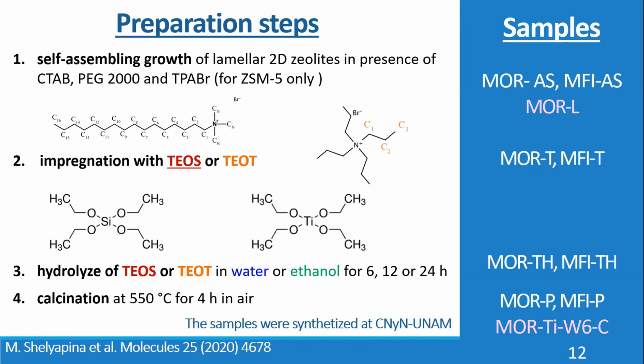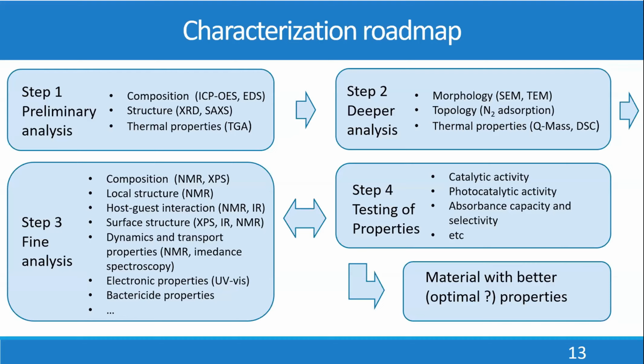Then hydrolysis occurs to form either SiO2 or TiO2 oxides between these layers, and calcination to evacuate the organics. All the samples were synthesized by our colleagues in the Center for Nanoscience and Nanotechnology at UNAM in Mexico, but all the studies were carried out at our university.